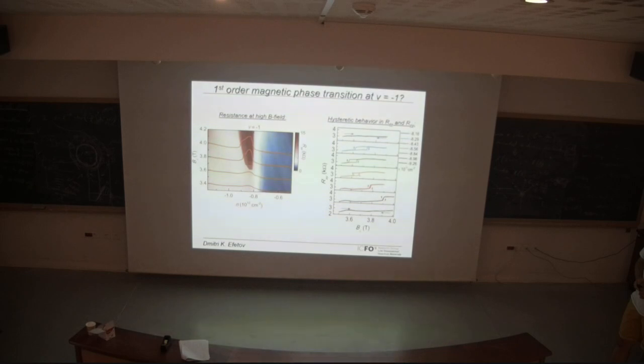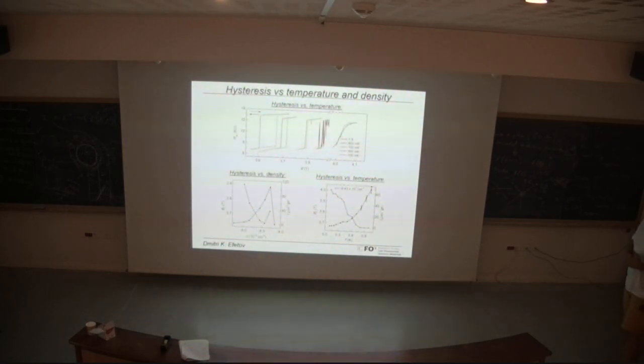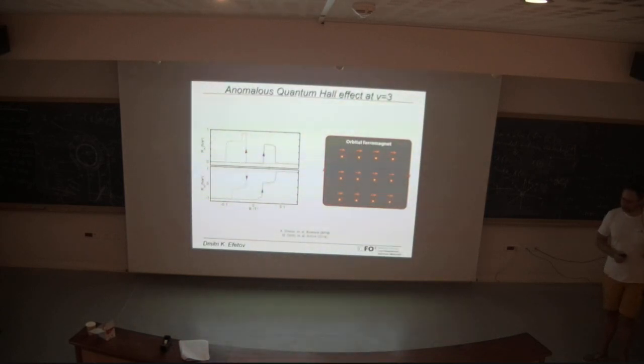Okay, and the current understanding right now is that this hysteresis vanishes with temperature. If we go above about 1 Kelvin, this hysteresis loop completely disappears. The hysteresis also vanishes with density. If we tune left and right, hysteresis disappears as we go away from the integer filling. And the current understanding is that these states have something to do with potentially orbital ferromagnetism, where the underlying ground state is an orbital ferromagnet at 0 field. And this orbital ferromagnet at 0 field can also induce an edge state, which then corresponds to Chern number 1 or 2 or 3 or whatever. And this state can survive at 0 field.